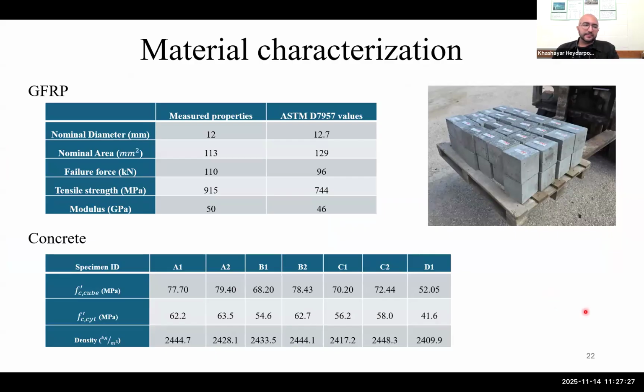Before testing the specimens, the material characterization was carried out on the number 4 longitudinal GFRP bars. And also the concretes were tested using the cube test that is more popular in Europe. But ASTM uses the cylinder test made mostly in the US, and the equivalent cylinder test results are also brought in the paper. So overall, it was designated for specimens A, B, and C to have the compressive strength of 72 megapascal, and specimen D to have the compressive strength of 43 megapascal.